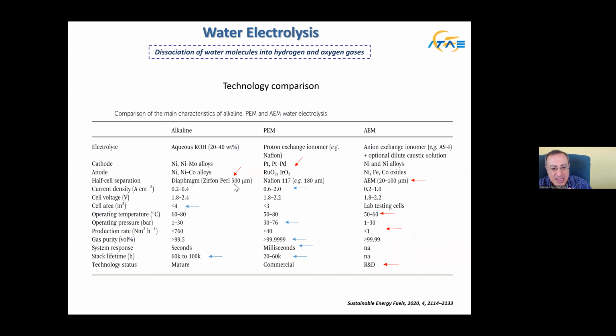Now, in this slide, this is an overview of the materials that are used in low temperature electrolysis technologies, alkaline, PEM, and AEM. In the alkaline electrolysis, essentially we use non-critical raw materials. Of course, there is some cobalt, but cobalt can be replaced. But we use a nickel-based electrocatalyst. We use a diaphragm separator based on zirconia. And of course, this is stainless steel for the bipolar plates.